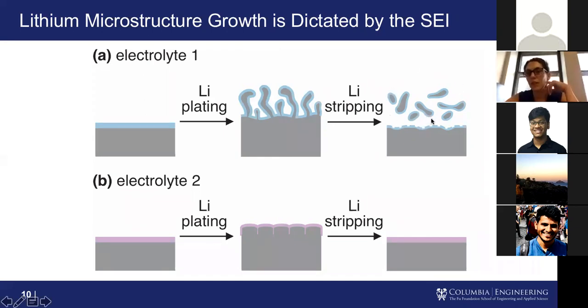And so you end up getting these chunks of lithium that are actually separated from your original anode. This is called electrochemically inactive lithium, and this is what's going to lower the efficiency of the battery. So if we have a scenario like this after stripping and we go to plate more lithium again, it's not going to plate here, it'll plate here, but now all this lithium is lost and we can't use it to do a reversible reaction anymore. So this scenario is bad for many reasons.